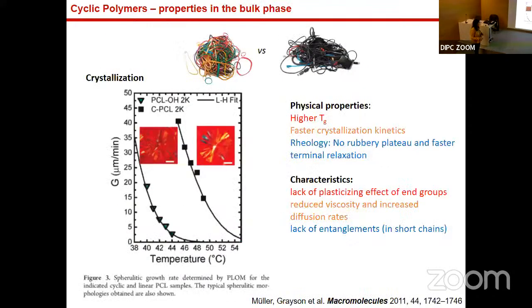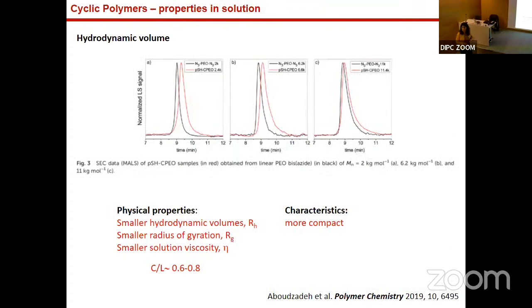There are also other physical properties. For example, the rheology is different, they behave differently. They don't show a rubbery plateau and show faster terminal relaxation, which is related to the lack of entanglements in the short chains. In solution, they also have different characteristics in comparison with the linear ones, which are related to their size. For example, hydrodynamic volume. They have smaller hydrodynamic volume in comparison to the linear ones, smaller radius of gyration, and smaller solution viscosity. The ratio of these properties, cyclic against linear, is about 0.6